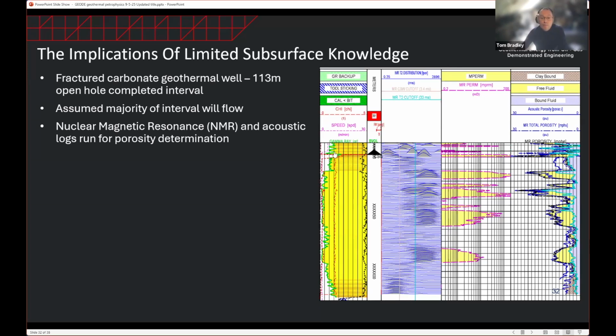The first track is our gamma ray. You can see the gamma ray here is reading low, suggesting a very clean formation. The next track is our nuclear magnetic resonance T2 distribution. As I mentioned earlier, for those not familiar with how to interpret these, you can look at the peaks. If you have a lot of peaks to the left, it means you have lots of small pores, lots of clay-bound porosity. If you have a lot of peaks on the right, you have lots of large pores, potentially movable porosity. Lots of peaks in the middle means middling-sized pores. These are most likely to be irreducible porosity that will probably not flow.